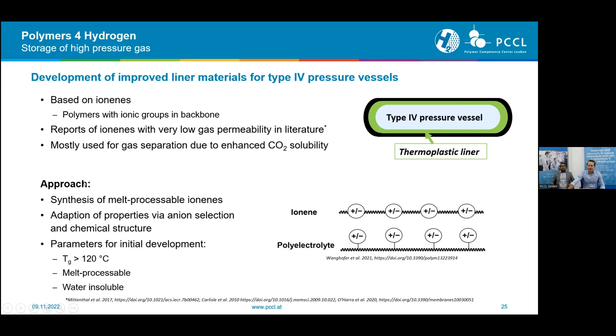The approach here is to synthesize melt-processable ionenes, because as I said, in literature they are usually used for membranes, and they are mostly producing the membranes via solvent casting, which of course is not very suitable for the liner fabrication. And then we adapt the properties of those ionenes by selecting a corresponding anion. And of course, we change the chemical structure, so the linkers, so to say, between those ions.